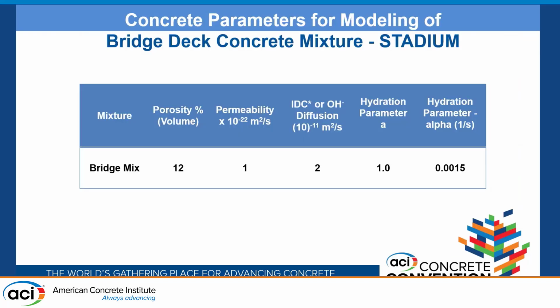These are the parameters from a Stadium run that we had. That too looks like a high number, but then it's multiplied by the porosity, and because it's on hydroxide, it actually ends up being a diffusion coefficient in the upper 10 to the minus 13 range, meters squared per second. So that's the game.